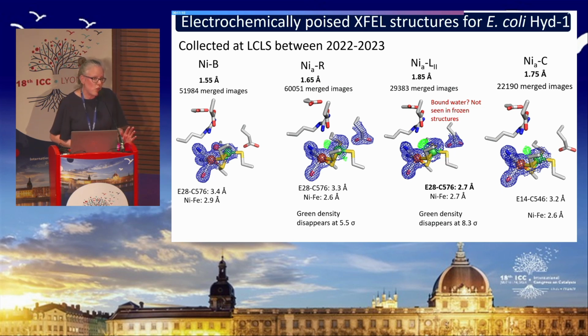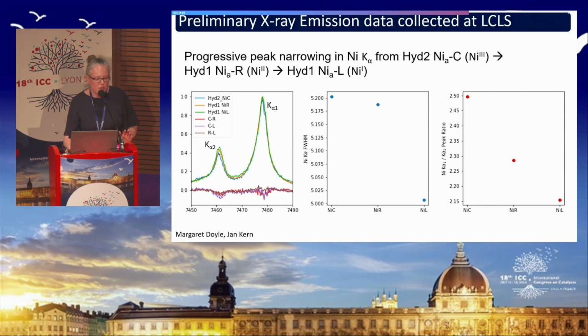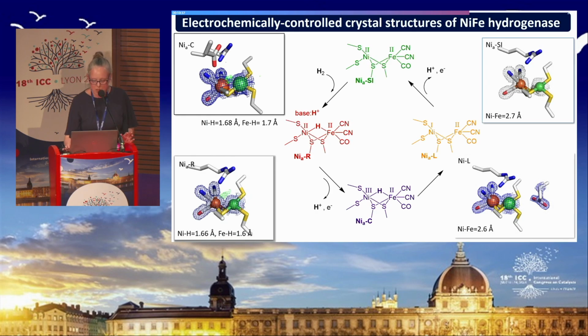They also confirm that our other structures recorded on the synchrotron are damage-free, because the XFEL records the data so quickly, before the crystals have time to be subjected to X-ray damage. So this gives us confirmation that the structures we were looking at before are all avoiding any photon damage that can be a real problem in metalloprotein structures. So this is sort of the start of some time-resolved work that we're moving towards now on the XFEL. I'm going to skip over that one.